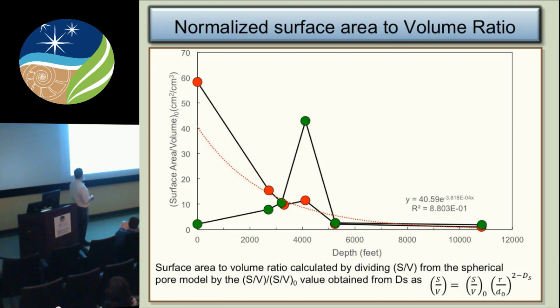And from the fractal scattering, we can calculate this total ratio. This D0 is a ruler length. R is actually the correlation length in the sandstone. And by combining those two, then, we can calculate the surface area to volume ratio for that sample as a function of depth. And you can see that what happens now at the highest scales, at the least depth, this is the surface stuff, these have the overgrowths growing on them. So this is altered material. That's the material with the least amount of overgrowth.